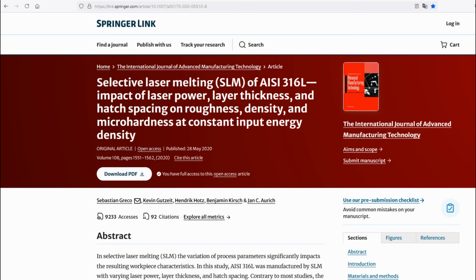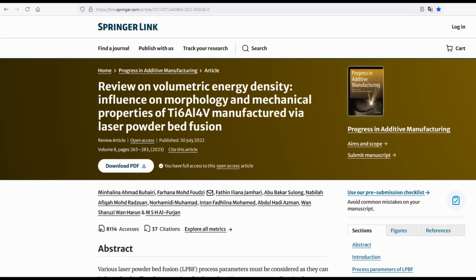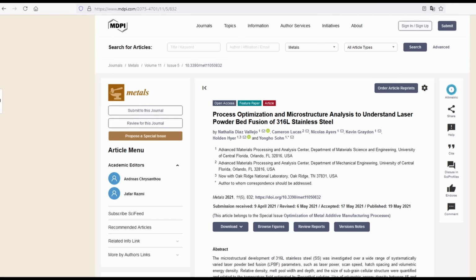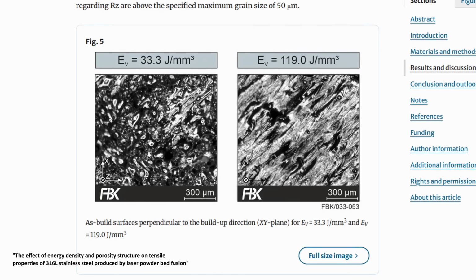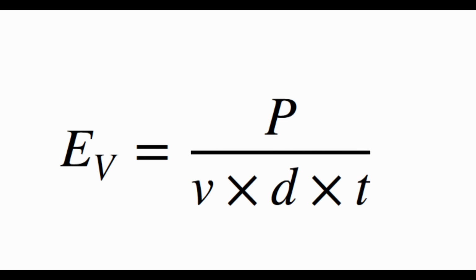Well, actually that's not quite the truth. There is a fairly simple concept called volumetric laser energy density, which is used as an index for performance. It's said to influence everything from surface finish to microstructure, and the formula is composed of the laser power, scan speed, hatch spacing, and layer thickness, giving the applied energy per unit volume.